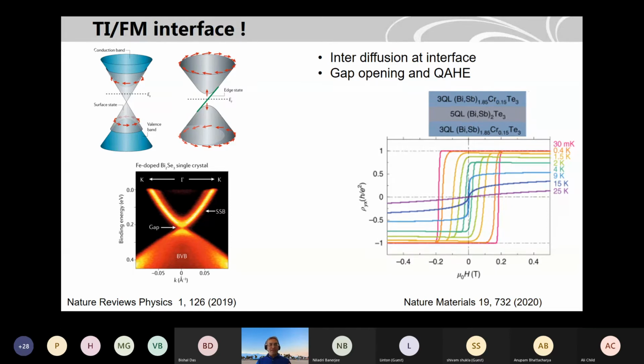So for the topological insulator, you have to retain the symmetries. But if you apply a magnetic field, or you deposit some magnetic elements on top of your topological insulator, or you dope it by some means, then you break the time reversal symmetry and you open a gap here. And within this gap, you have one edge state which is coming up here. And what people see in such systems is a quantum anomalous Hall effect. So this was quite challenging.